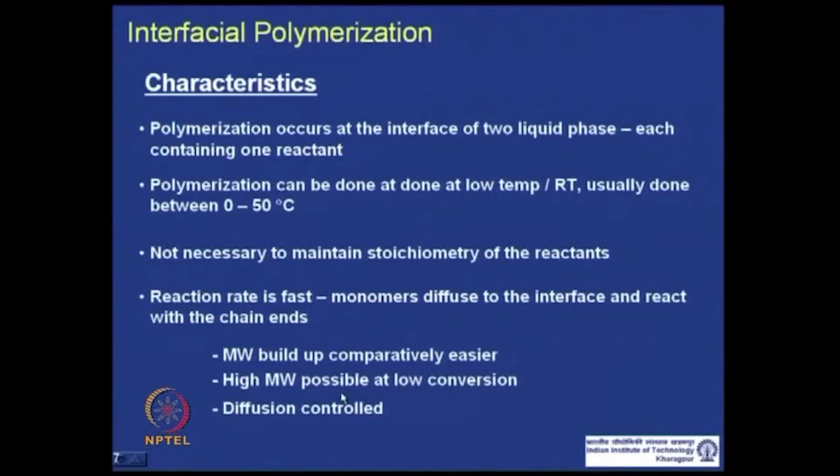and as the monomers get added at the end of the chain, high molecular weight is even possible at low conversion, unlike the normal polycondensation or step polymerization process. And because the diffusion is slower compared to the actual polymerization reaction, these polymerization reactions are often diffusion controlled.